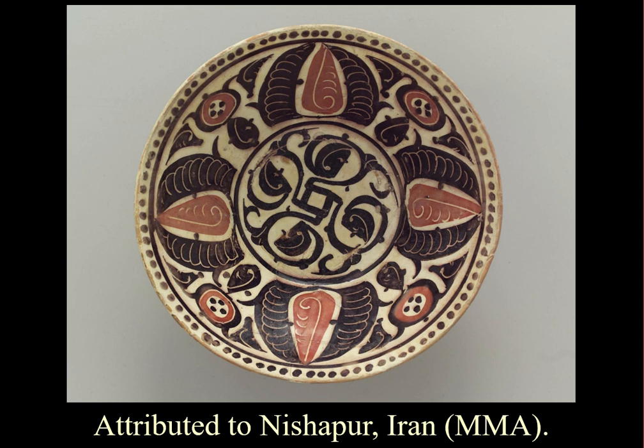This one is also attributed to Nishapur but not certain. This would actually be a useful thesis — distinguishing between production centers for this kind of pottery. I have done some petrographic analysis and the way of incising through the slip paint I would actually associate with Samarkand. But since I can't thin-section this piece because it's whole, I can't test that. With a greater sample size it might be possible to say that with more surety.